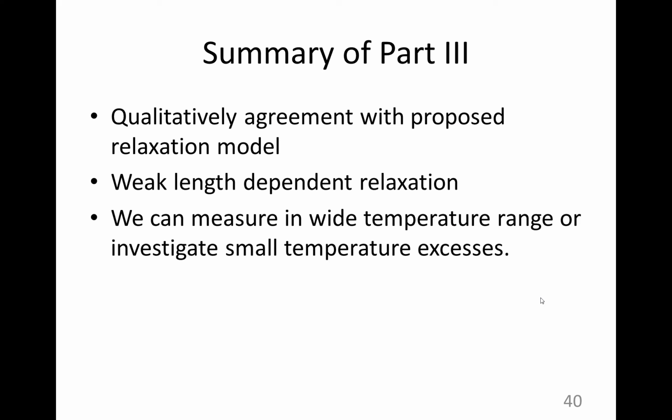And based on the two thermometry methods that we have, the switching current method and the probability method, we can measure the thermal processes in a wide temperature range. This is the switching current method, and we can also investigate small temperature excesses, which is a property of the probability method.